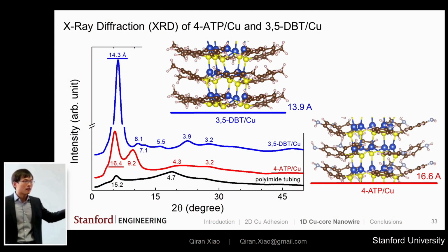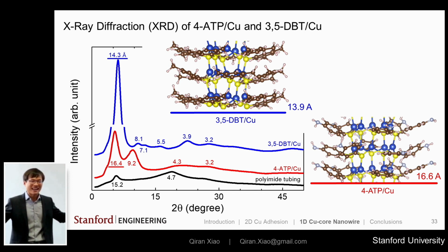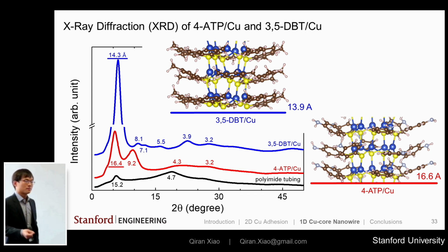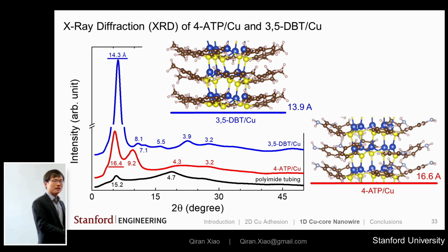So what's happening here is that many of the extremely thin 16 angstrom diameter nanowires are tightly bundled together to form our material in the nanowire's radial direction. And that tight bundling gives substantial presence of periodicity along the nanowire's radial direction in terms of nanowire diameters. And that leads to the peak being detected by XRD and showing up as very intense peaks.